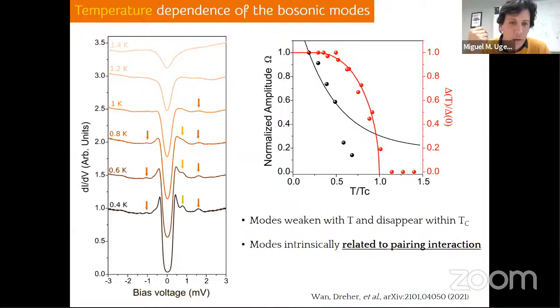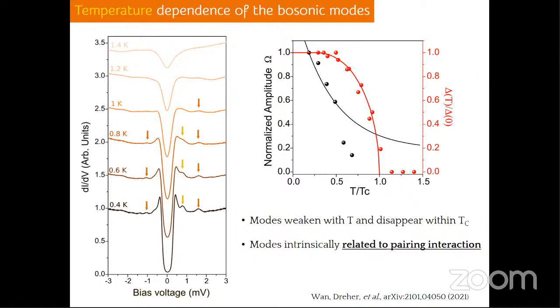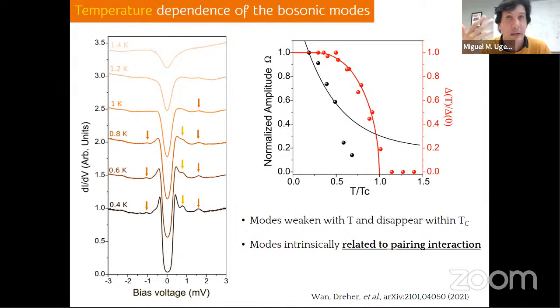Yes, that is totally true, but I don't think that's against the idea of having a spin excitation. I cannot give you a good insight about why it remains constant with the temperature, but I don't see how temperature could affect the binding energy of these bosonic modes. I do understand that they become mobile when you apply a magnetic field, because it's a result of a magnetic excitation, but I don't understand why this peak should move with the temperature.